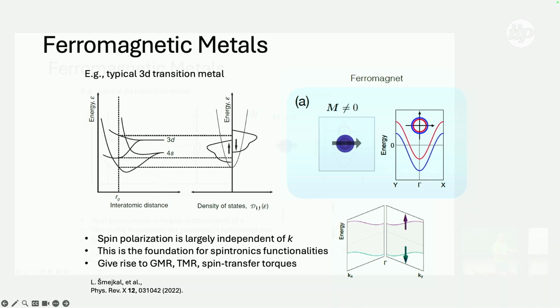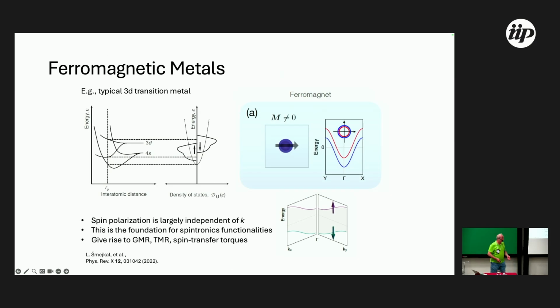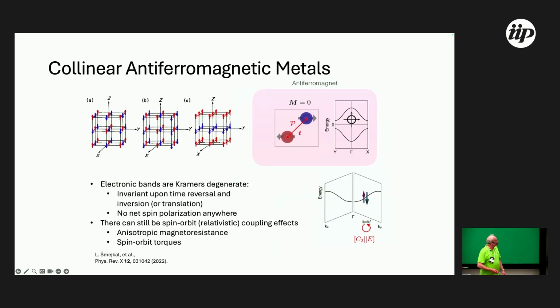We get a splitting of the d bands, and that gives rise to a net spin polarization, right? We have these two bands for spin up and spin down that are shifted with respect to each other. And if you look at the Fermi surface, essentially you get an isotropic spin polarization in ferromagnets. And it makes it very useful for magnetoresistance, memory, all this kind of stuff.